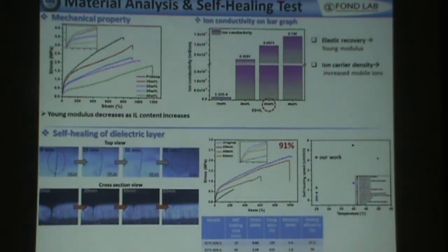So for the material analysis here, to determine the optimum amount of ionic liquid needed for effective device fabrication, we introduce different concentrations of ionic liquid into our system and analyze its mechanical properties. So we can see from the UTM data that the Young's modulus decreases as the ion concentration increases. On the other hand, we can see that with higher ion concentration, the ion conductivity increases.